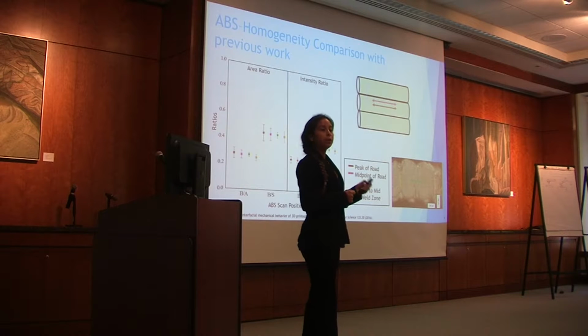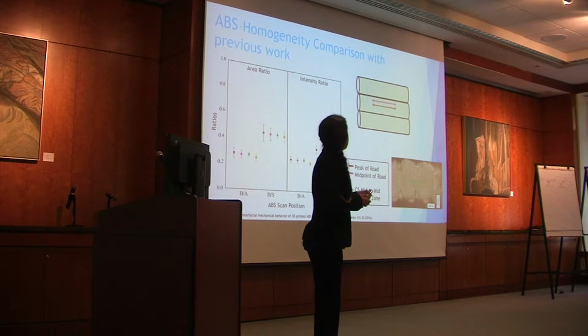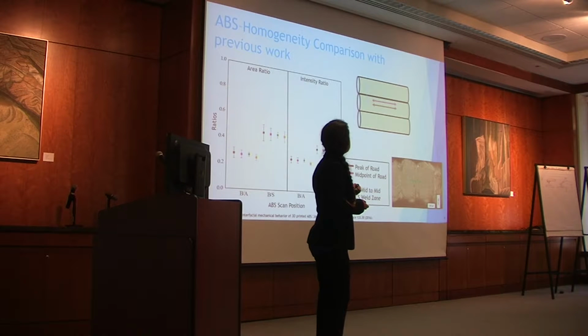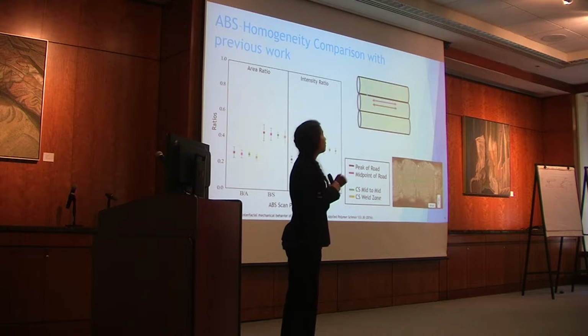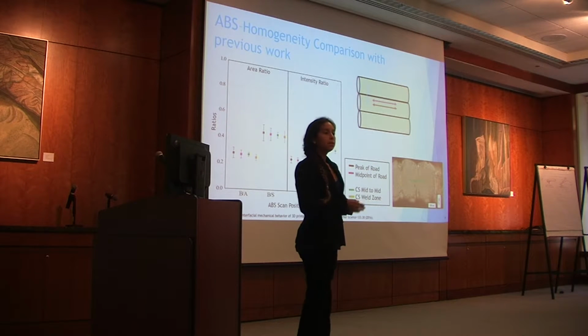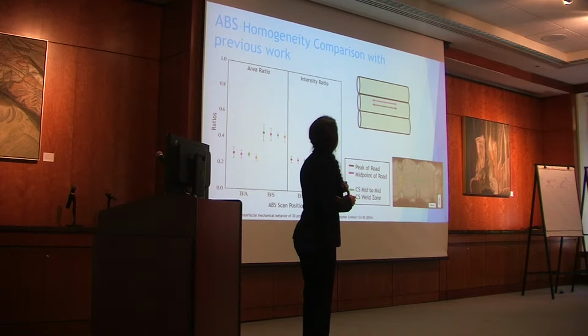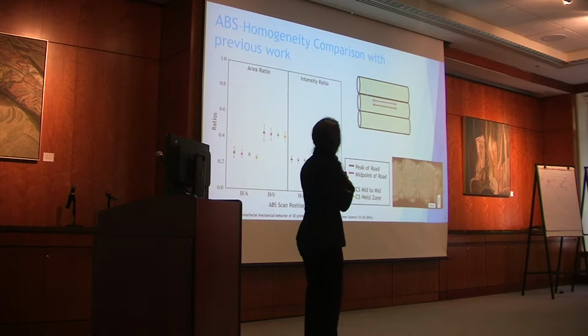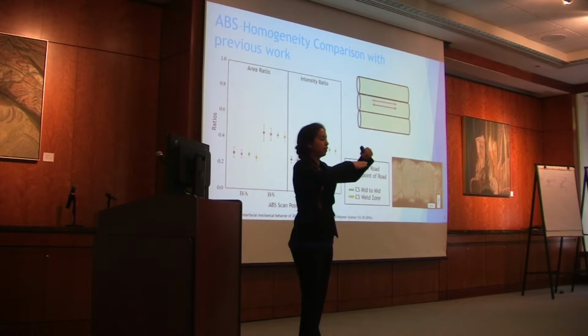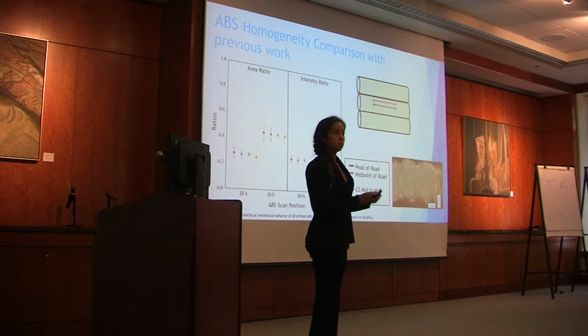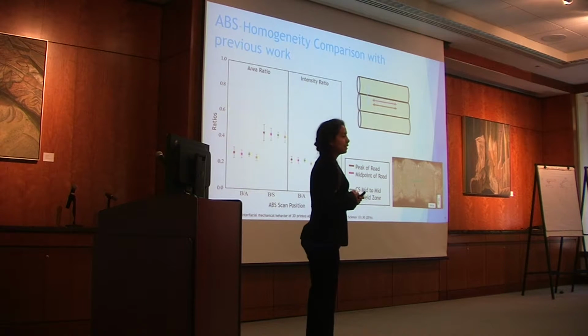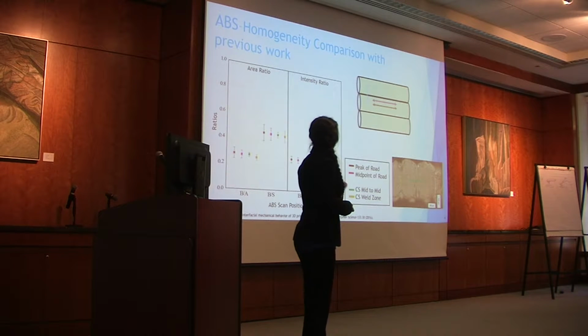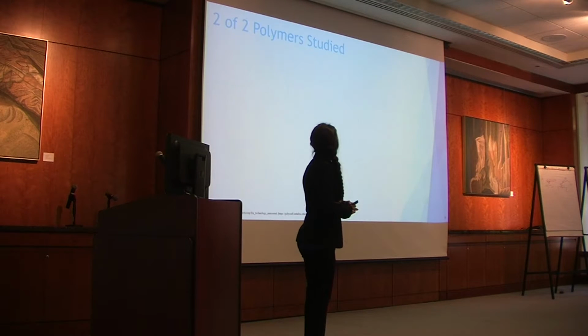So this is different than previously published work. In previously published work, they said that there was approximately a 30% decrease in the ratio through this interfacial region, where the overlapping was occurring in the printing process. Reasons that we may have seen differences could have been because of the way that they did their mapping. When you go through a road like this and go from a peak to a different view of focus and back to that peak, you can run into topography issues, which can easily happen and can then affect results. I also looked at the cross-sectional area, and they all fell within each other, so this was great for us to see.